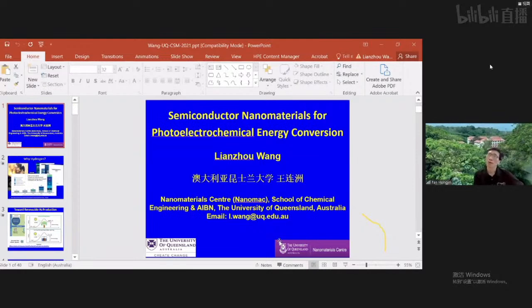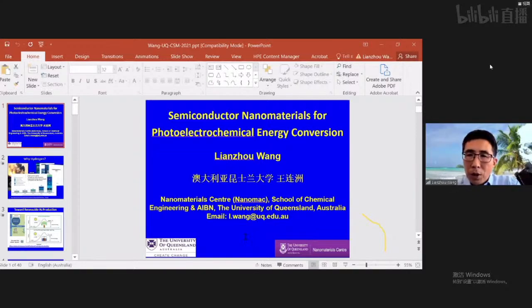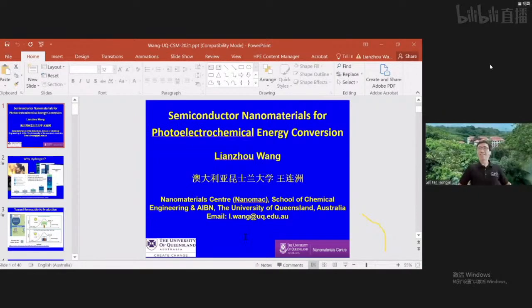But like the old conventional quantum dots, they can have this rainbow effect, right? They can tune the band gap, so they can absorb wide broad spectrums. Is this also possible for the perovskite quantum dots? I believe so, yes. For this type of quantum dots, we can tune the composition as I showed in the slide, and by simply changing the composition and also changing the quantum dot size, it can be in a very broad range. I see. Thank you, Lian Zhou.